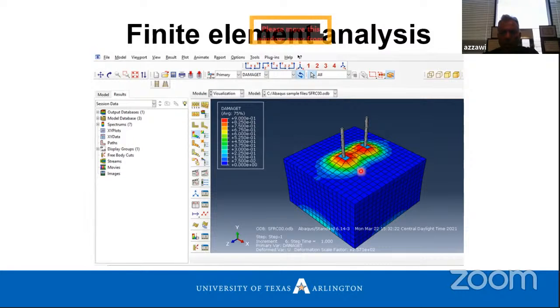So as we see, we have the concrete breakout failure around the bolt. This is from the finite element, and it should match what we have in the actual experiment. In the actual experiment, as we see, we have this grouping action effect, and we have this damage. It seems like we have one anchor damaged in this area, and that's expected. That's what we have in the finite element also. This is for the plain concrete, so we have a huge damaged area here. This is for 0%. This is the experiment, and this is the finite element analysis.